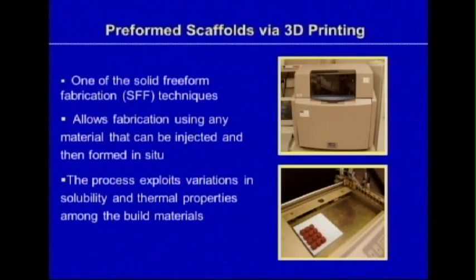Now, how about another way? What do we use? This is our piezo inkjet printer, and this works by making a solid out of 2 things. So rather than laser photo initiation, this uses polystyrene and it uses wax. It uses a medium length wax that melts at about 65 degrees centigrade. And so when we put the STL file in this machine, rather than either remain liquid or solid at each level, you get either the wax or the polystyrene at each level, and the company puts colorants in them so we can see the difference in color.